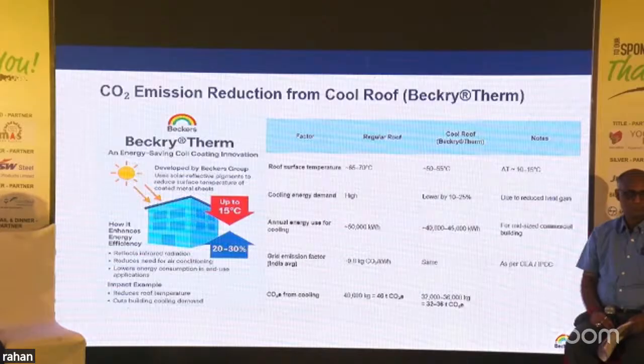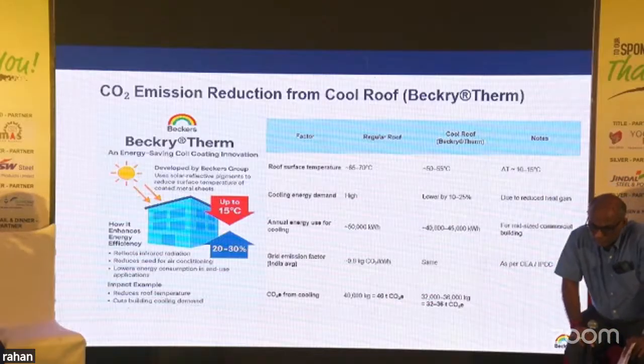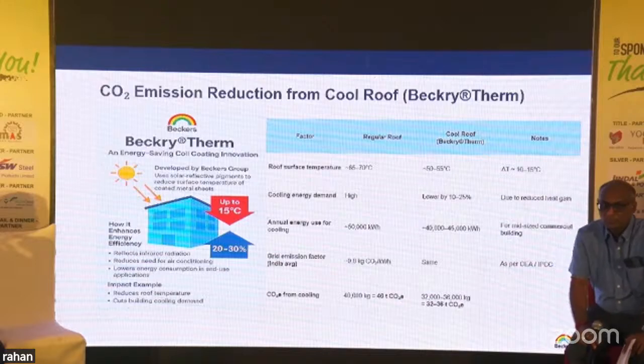When we think about sustainability, it is about scope 3 as well. We have developed a beautiful paint system called Beckry Therm. It reduces the surface temperature of the coated steel by 15 degrees Celsius. It means a reduction in energy consumption, in the energy bill as well. We have a special pigment in the paint system which reflects a lot of solar energy back to the atmosphere, so it reduces the energy consumption by 25%. In a country like India, where AC is not a luxury but essential, we can think about this system.